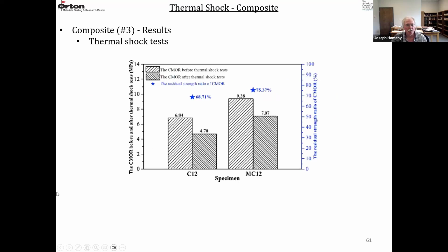So finally, when they do the thermal shock testing, this is the cold MR before and after thermal shocking, and then the residual strength here in blue. So C12, coarser material, MC12, finer material. And actually, the finer material is stronger before thermal shock testing because the coarser material obviously has the coarser particles, which gives bigger flaws and lowers the strength. So MC12, better initial strength and more retained strength.